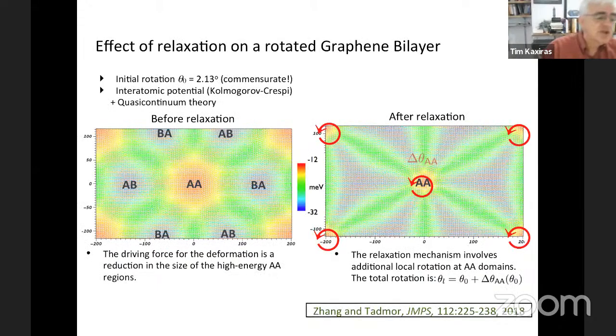So one important question is what happens to the atoms? I showed you the overall distribution of atomic sites when you put one layer on top of the other, but the atoms don't stay where the original layers were. They relax to minimize the energy. And the first detailed study of the effect of relaxation on the twisted bilayer graphene was done by this group, Zhang and Tadmor. And here's the picture that they produced using an interatomic potential to model the interaction between atoms, and that allows us to calculate the atomic relaxation.